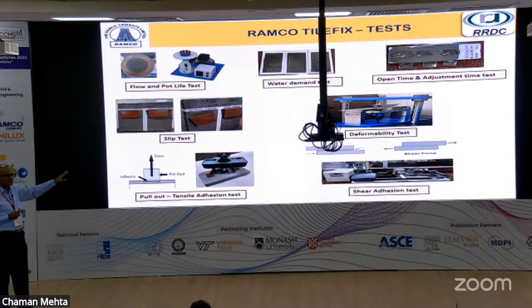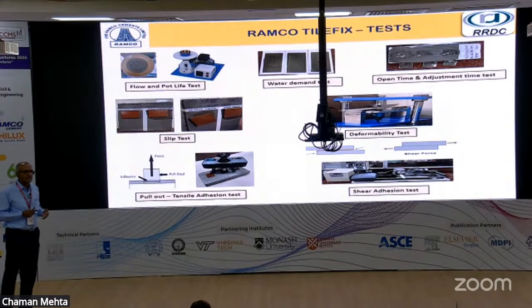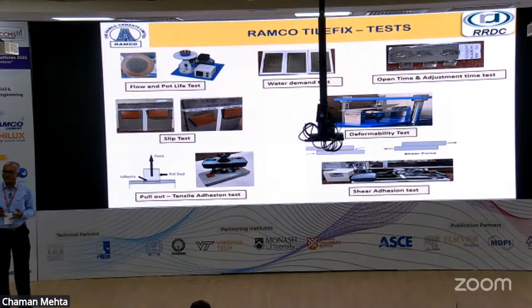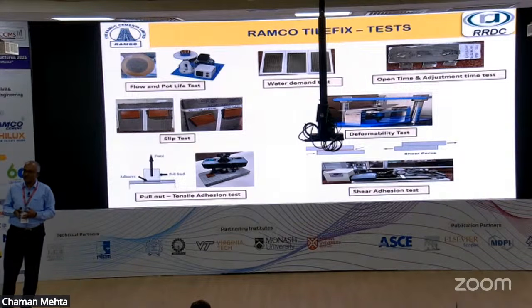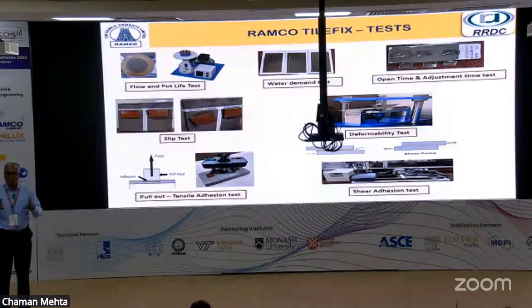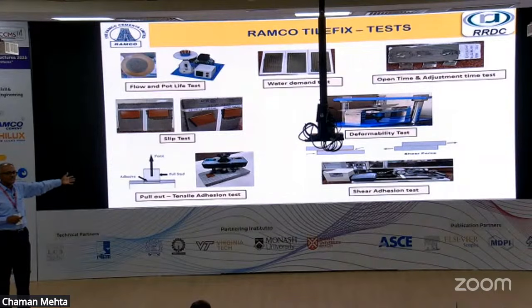The slip test, of course. As compared to cement mortar, it is always advisable to go in for tile fix because of the inherent disadvantages of cement mortar: it shrinks, and you cannot do curing. But as far as this tile fix is concerned, it is a self-curing product itself.